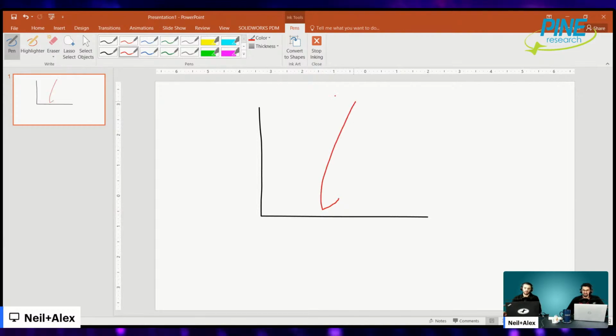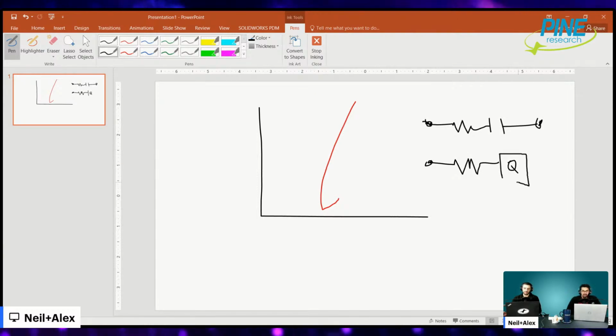That is a good point. Good piece of advice. But my point here is that if you fit either a capacitor or a CPE, if you do the capacitor, the worry is that it'll be an averaging kind of thing, and it's going to be a straight up and down line. It might sort of miss the value. If you allow for a CPE, what you'll probably get is a straight sloped line that will extrapolate. I'm trying to draw a straight line here and kind of failing, but if this is 0 here, you might extrapolate to something like that.